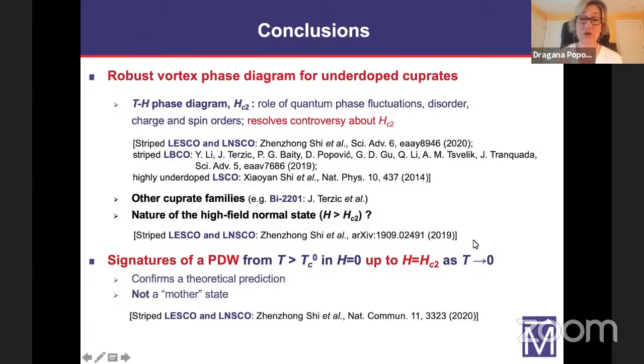Now, this reference on the Hall effect finds that in this high field regime, above the upper critical field, the Hall coefficient essentially vanishes over a wide range of temperatures and magnetic fields in the phase diagram. So the question is why? From the measurements that we have, there is no evidence for any Cooper pairs that may persist at such high fields, and other kinds of measurements on these materials, for example determining the spin gap, found that it's very low, not more than 1 milli-electron volt, maybe 2. So there is no evidence for that. That's the main question: why does the Hall coefficient vanish?